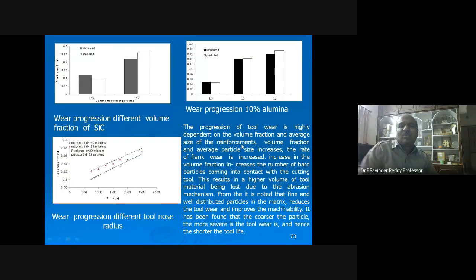The progression of the tool wear is highly dependent on the volume fraction and average size of the reinforcements. As volume fraction and average particle size increase, the rate of flank wear is also observed to increase. The increase in the volume fraction increases the number of hard particles coming into contact with the cutting tool. This results in a higher volume of tool material being lost due to the abrasion mechanism.